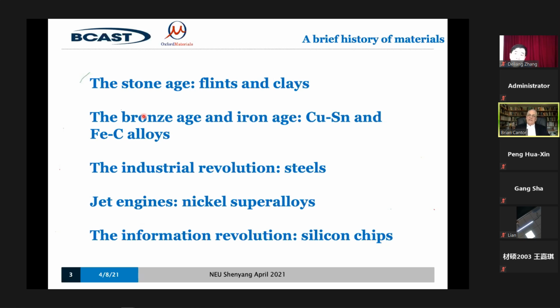But about 6,000 years ago, about 4,000 BC, about 6,000 years after the agricultural revolution and the end of the Ice Age, people discovered if you take some of the tin and you mix it with the copper, or more accurately, you take copper and you mix a little bit of tin into it, you get bronze, and you get a really good material. It's not soft like pure copper or pure tin.